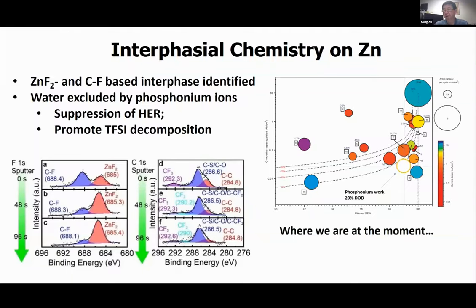And this is our best zinc anode material. We are still at this point, as shown in this figure, but we are making a lot of progress. We are rapidly approaching this goal. Coulombic efficiency above 99% is within our reach. But to do that, we still cannot use a very high C rate of charging and discharging.